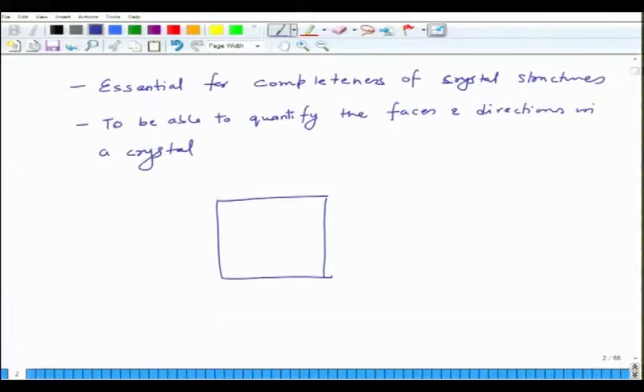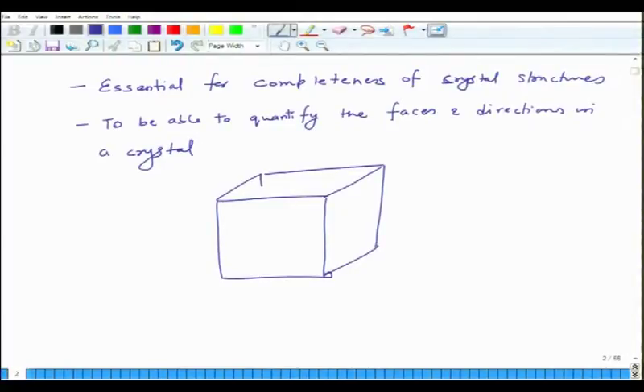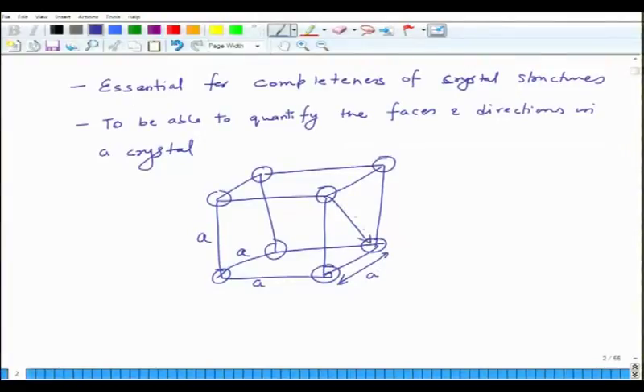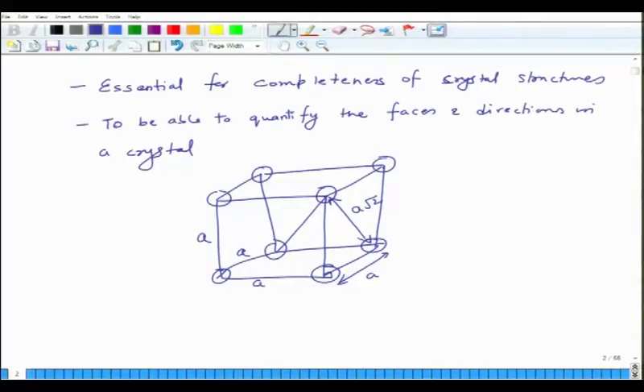Let me draw a simple parallelepiped here. You can see that the separation between these atoms is 'a', but between these other atoms it is not 'a' — it is something else, let us say a√2. The spacing between different pairs of atoms is different. So given that different atoms have different spacings with respect to each other, the properties also change in different directions. If I measure some response in this direction, it is different from the response measured in this other direction.